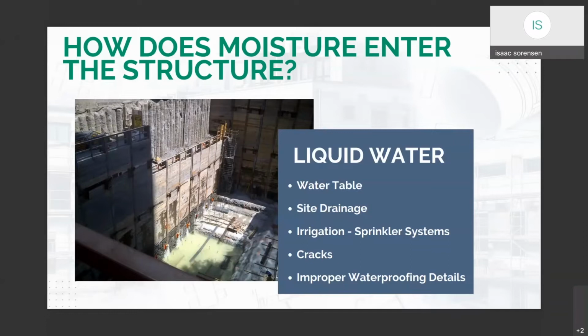And then there's cracks in the concrete. Of course, concrete always cracks. They're a prominent part of concrete. It will crack. The location of these cracks can somewhat be controlled by the design of the concrete. However, there is also the possibility for cracking to occur that has not been accounted for. Water can enter through these cracks, and so it's important for the system to be designed to accommodate cracking. No matter how good everything is, waterproofing details, we'll talk about this, continuity becomes really the most important factor in creating an effective waterproofing system.